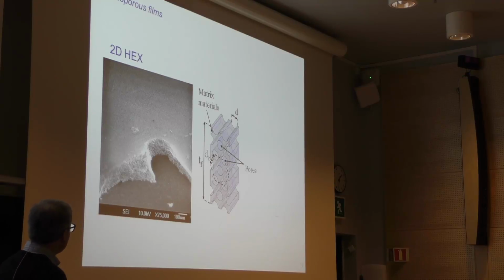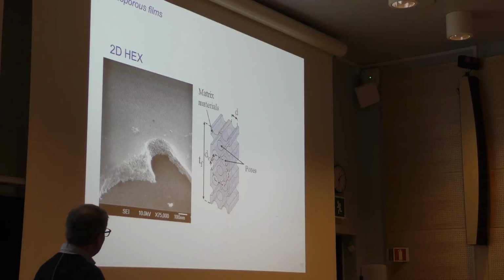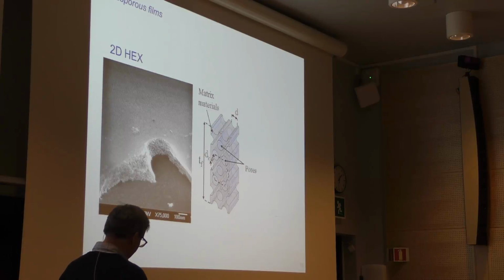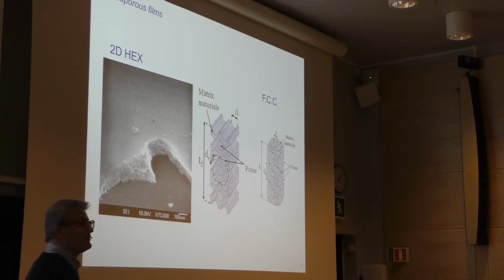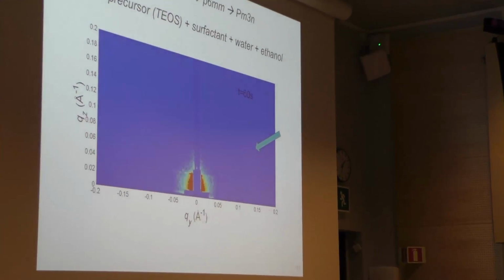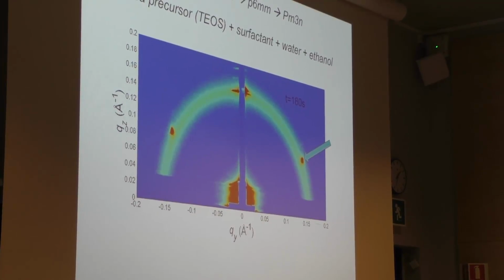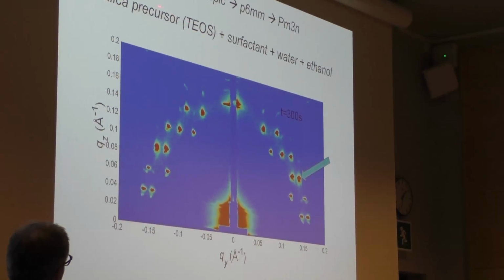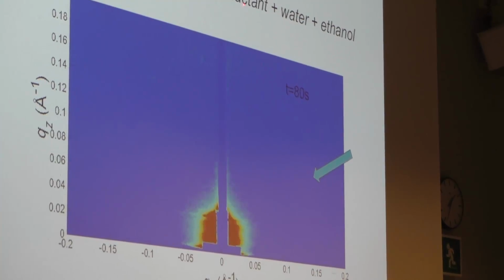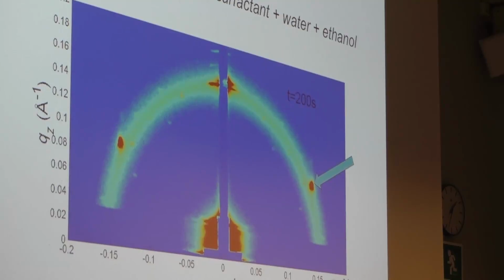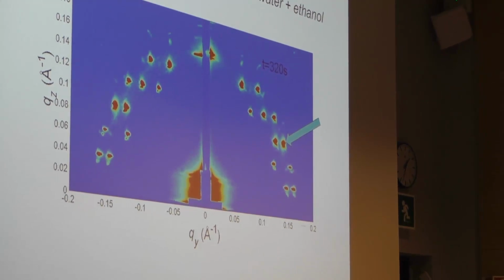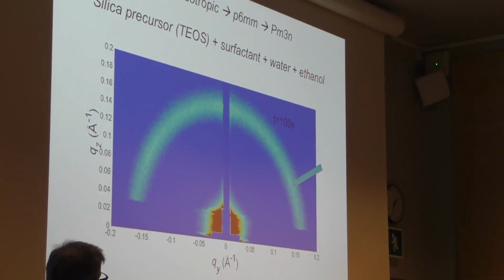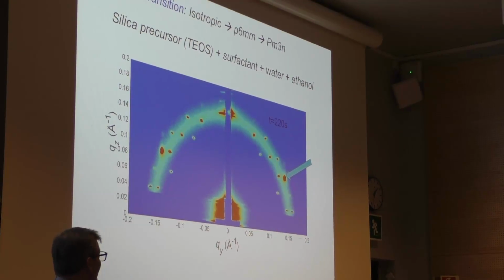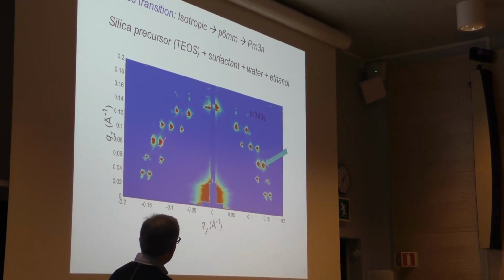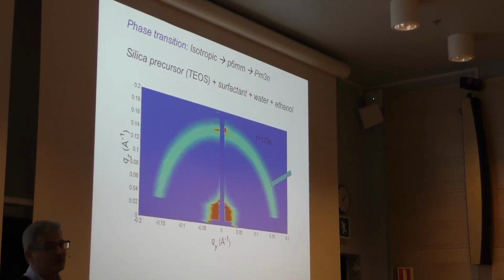They can, for example, be silicas, and they can, for example, be hexagonal, like the structure that is illustrated here, but they can also have, for example, FCC structures. And what I'm showing you here is a mixture of a silica precursor together with a surfactant, water and ethanol. What happens is that this ethanol gradually evaporates, and as a function of time, you can see that this diffraction pattern entirely changes, right?